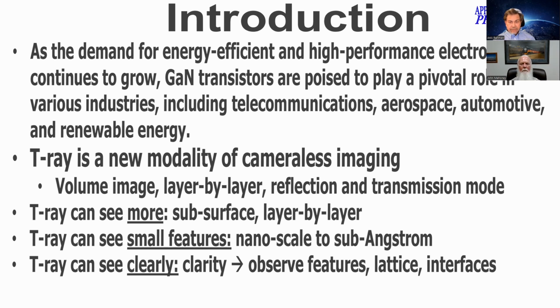T-ray is a new modality of cameraless imaging. It does volume and layer by layer, as I mentioned. It also has both reflection mode imaging as well as transmission mode imaging ability. And T-ray's main attraction is that it can see more. Whatever the camera misses, T-ray does not miss, and I will show you some comparison. But it also can see smaller features, and it can see much more clearly than anything else, be it X-ray, be it optical, be it AFM, etc. It can see much more clearly both the material, the lattice, and their interfaces.